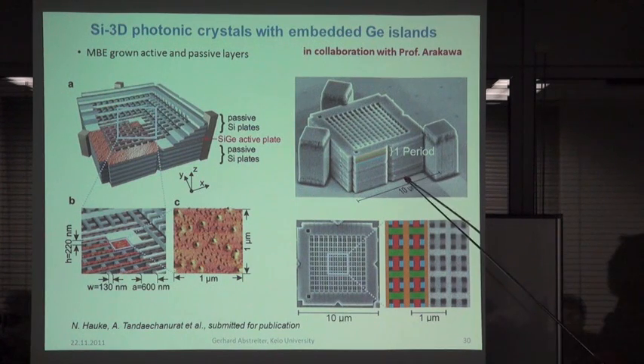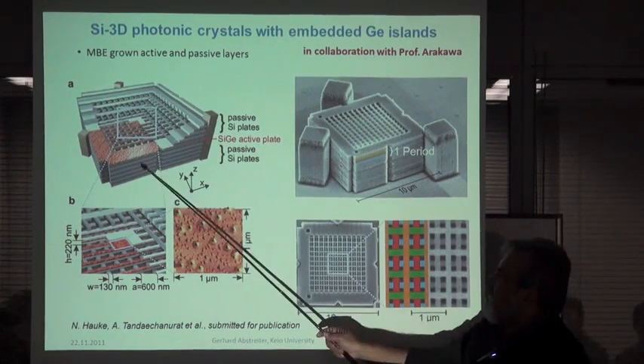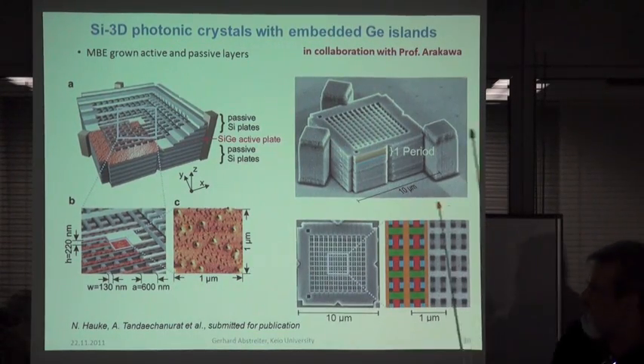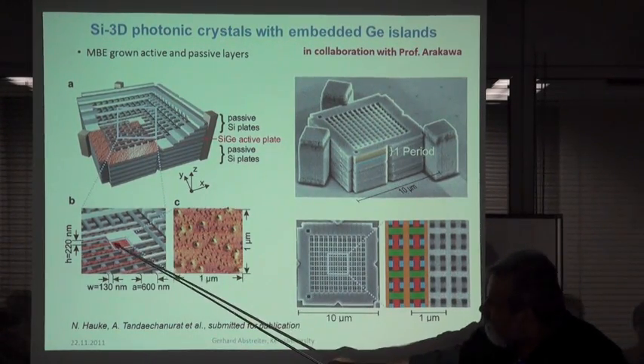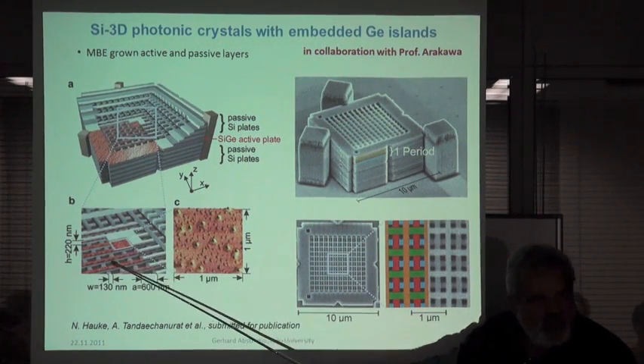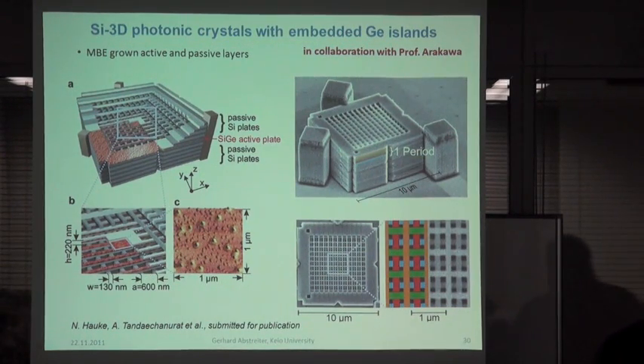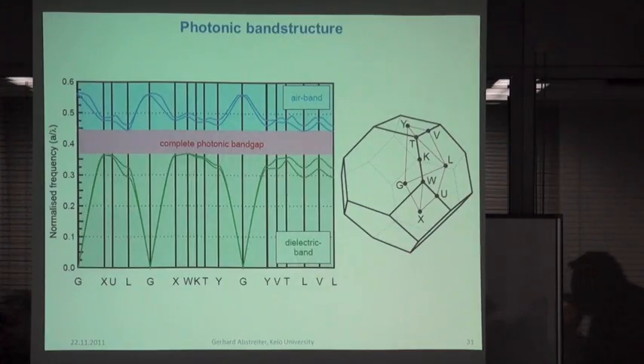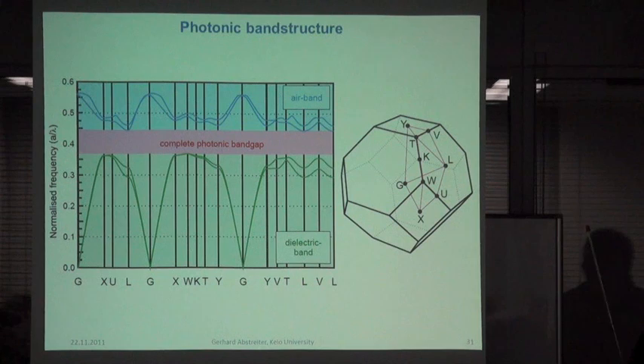So now we stack this on top of each other, but then we also introduced a defect. In the center we have placed one plate which has these germanium islands and has in the middle no lines. So it's in 3 dimensions now a photonic crystal cavity. And this, compared to the 2-dimensional photonic crystal, has now a complete photonic band gap in all 3 directions.